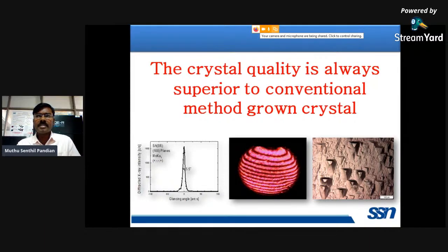This we have identified with several characterizations. For structural perfection, we have carried out the HRXRD measurement, that is a high resolution X-ray diffraction measurement. For dislocation density, we have carried out chemical etching. To identify the optical homogeneity, we have carried out the birefringence measurement. To identify the mechanical stability, Vickers microhardness; optical quality, UV-visible measurement; and electrical permittivity.